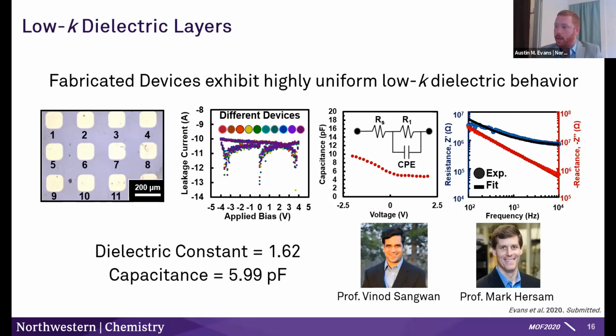So that's pretty good. And then you can look at the voltage capacitive response, and you can do some AC spectroscopies, and you can extract from those measurements that the dielectric constant is indeed quite low, 1.6, which interestingly is pretty close to a linear combination of the dielectric vectors I showed on the past slide. So this was done by Professor Mark Hersam and Professor Vinod Sangwan at Northwestern, and this was a really exciting measurement for us because it sort of validates that the strategy we used to generate these highly uniform films has some technological relevance. This is sort of taking things to the next level, in my opinion.